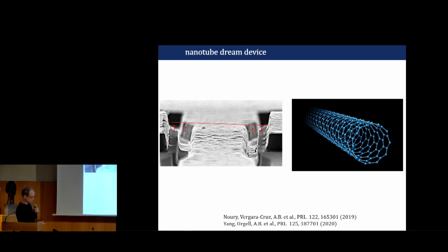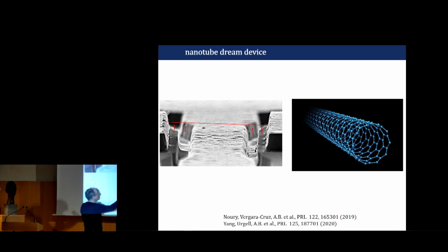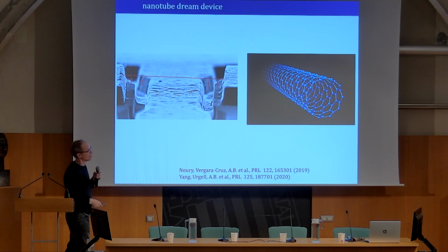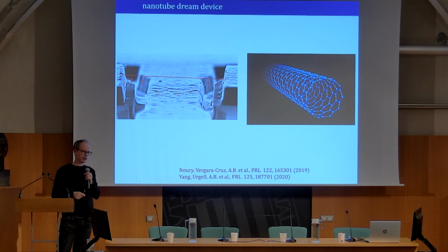And we say that we are able to produce nanotube dream devices. We say this because we are able to grow carbon nanotubes where there is no missing carbon atom along the suspended region of our device, with essentially no adsorbed molecules on the surface of the nanotube, and, what is also important, with the nanotube suspended far away from the charge fluctuators here and here in the dielectrics. Charge fluctuators are bad for nanotube devices, and electron devices in general.